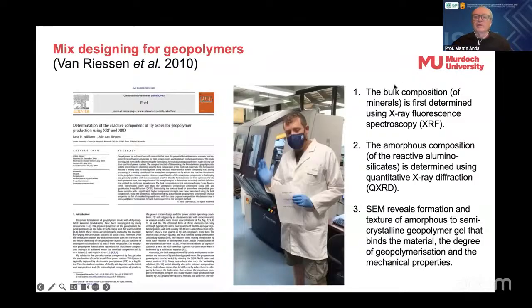So we do that by determining the bulk composition, firstly with X-ray fluorescence, and then the amorphous composition of the reactive aluminosilicates is determined by using this quantitative XRD method. And then we can also use scanning electron microscope there, point number 3, to reveal the formation and texture of amorphous to semi-crystalline geopolymer gel that binds the material, the degree of geopolymerization, and the resulting mechanical properties that we get after we've prepared the mix design and done the cast, and then we want to start testing it.